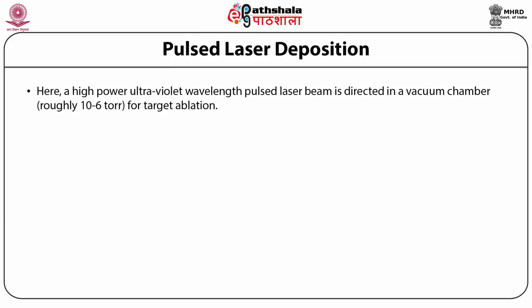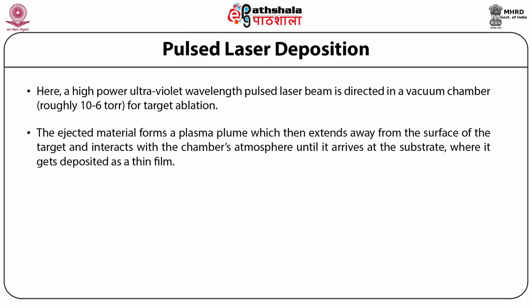Here, a high power ultraviolet wavelength pulsed laser beam is directed in a vacuum chamber, roughly 10 to the power minus 6 torr, for target ablation. The ejected material forms a plasma plume, which then extends away from the surface of the target and interacts with the chamber's atmosphere until it arrives at the surface of the substrate, where it gets deposited as a thin film.